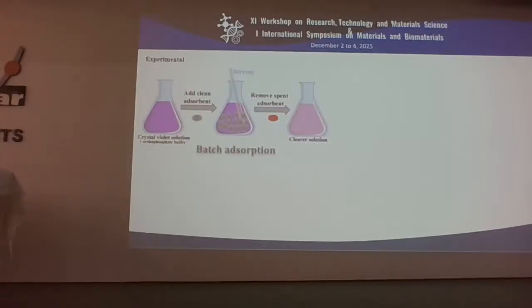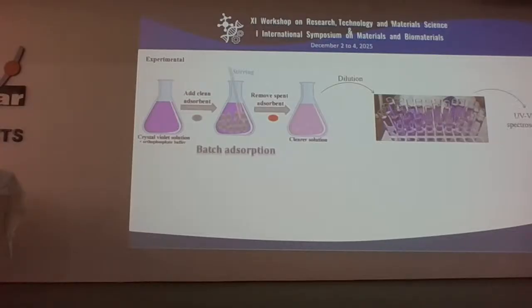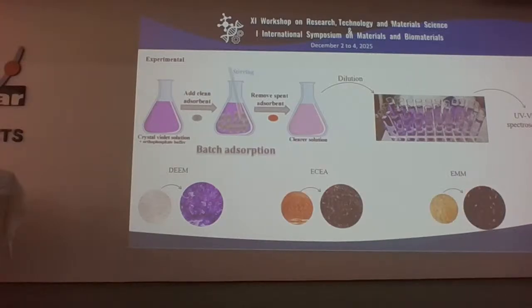So the experimental phase to test the adsorption is to use a solution of crystal violet. I use a buffer to maintain the pH, add a clean adsorbent, which was my chitosan, and remove that adsorbent. With the clear solution, I did some dilution. After that, some UV spectroscopy. And this is the color of my modified chitosan at the end of my adsorption. As you can see, maybe by the color, the DEEM is better than the ECEA and the EMM.